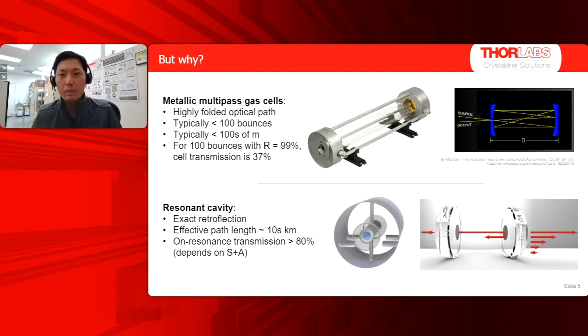And then if you take it to the extreme, and rather than have a highly folded optical path, if you take it to the limit and just fold that path back onto itself, you have a resonant cavity, a Fabry-Perot cavity. And in this case, with very high reflectivity dielectric mirrors, you can achieve tens of kilometers of optical path in sub-meter long cells. And when you're on resonance of these Fabry-Perot cavities, you can get typically with good mode matching and good losses up to 80% or more transmitted when you're on resonance. And again, that maximum transmission is going to be dependent on the breakdown of your transmission versus your parasitic losses.